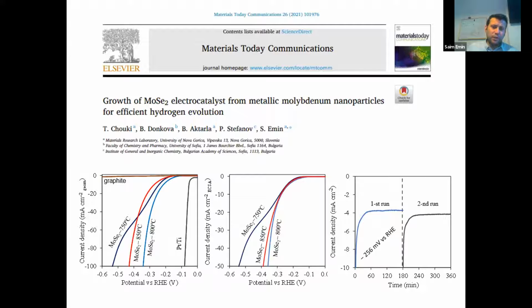And using the same method, we grew molybdenum diselenide films. As you can see here, we have different films annealed at different temperatures: 750, 800, 850. We also measured the area of the films and then normalized it. After normalization, we saw that basically 800 and 850 give the same activity.